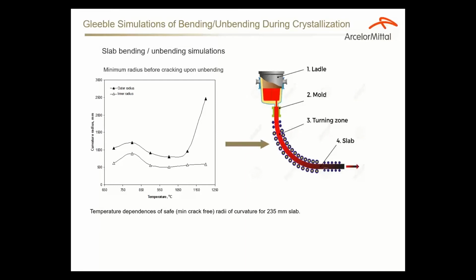Another thing where we use another aspect of our application to casting is, typically if the caster is curved, the liquid steel goes down and is being bent and unbent as it crystallizes. This kind of deformation can also induce fracture of the slabs, cracking, and other very unpleasant things. So part of our task was to determine what is the safe curvature radius that this particular steel grade can sustain during crystallization. This is just an example for one of our steels.